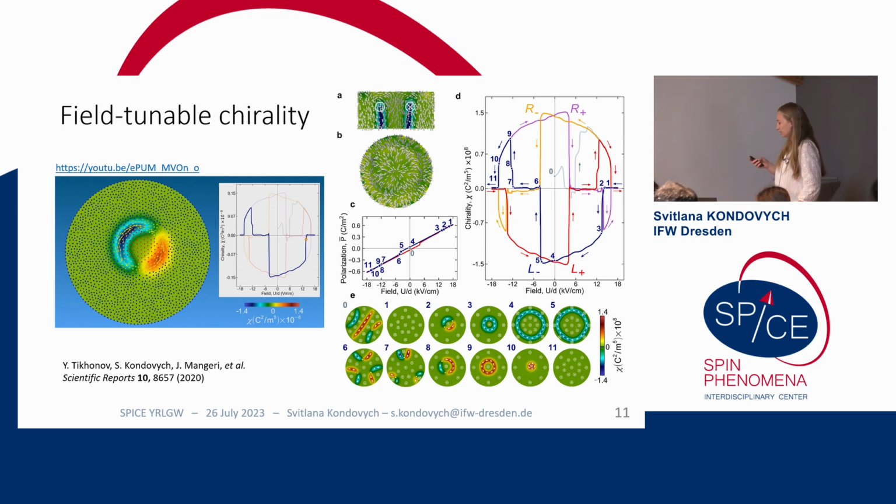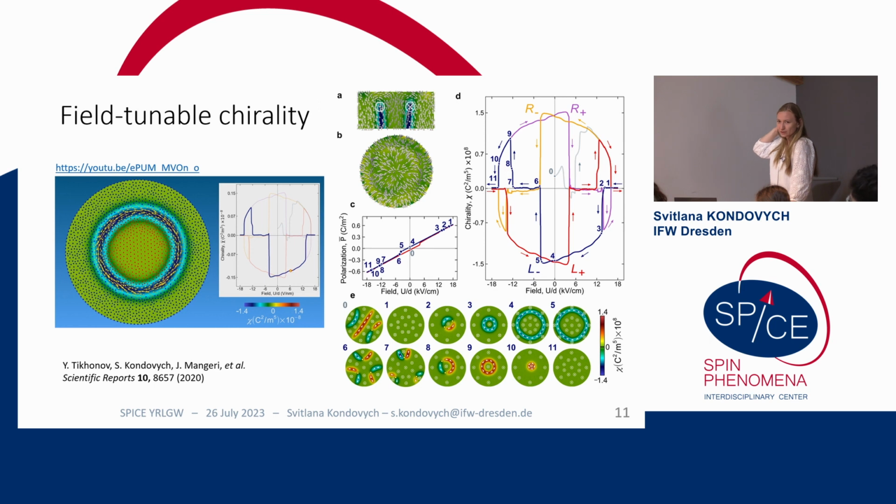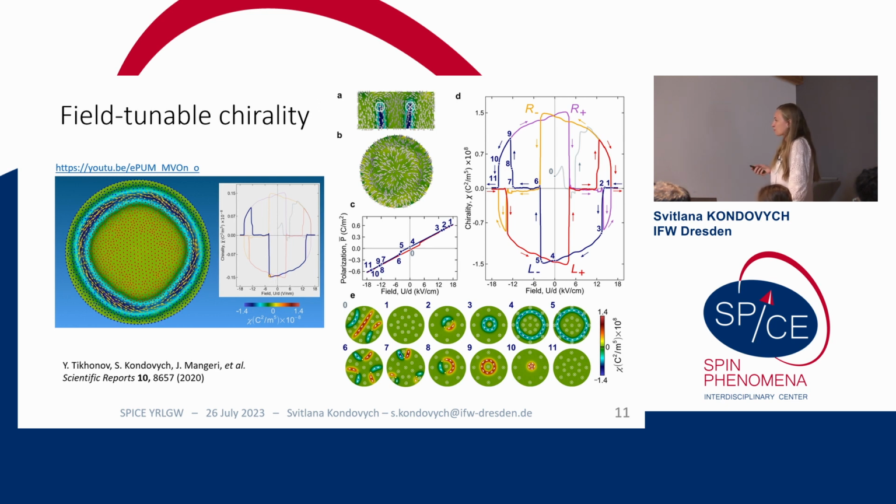So at the moment the blue domain wall for this skyrmion appears. These skyrmions are Bloch type because Néel skyrmions are not favored for the same reason, for the electrostatic interactions and the necessity to avoid the depolarization charges.